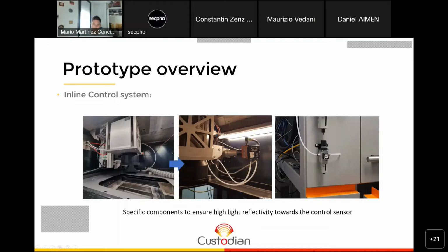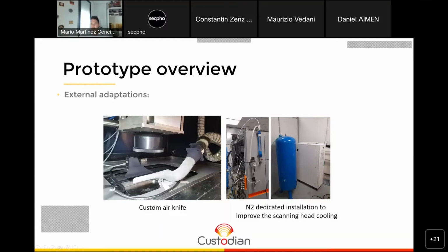So as you can see here, the camera is attached to a camera adapter, which is this one, and here we can find steering mirrors where the infrared light comes back to the camera so that it can be analyzed and processed. And here some other additional installations that we have to do: a custom air knife to prevent the dust and contamination from coming to the F-theta lens, and a dedicated nitrogen installation to cool down the scanning head galvo mirrors, because the damage threshold is affected when you change from one shape to the other. So we found plenty of issues here, but hopefully we were able to sort them out.